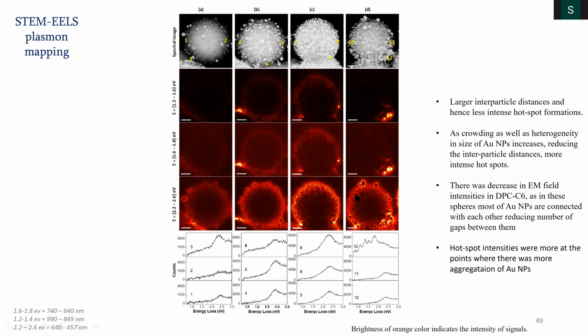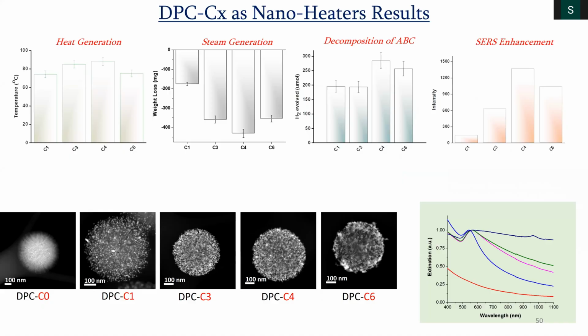Whereas here, you have more gold particles, but they started connecting with each other. So you see now the brightness decreases because now they have no gaps between them. They are connected with each other. So you need gaps to have a hotspot. So that's what we saw in the EELS studies. So all our studies show that C4 is the best material.